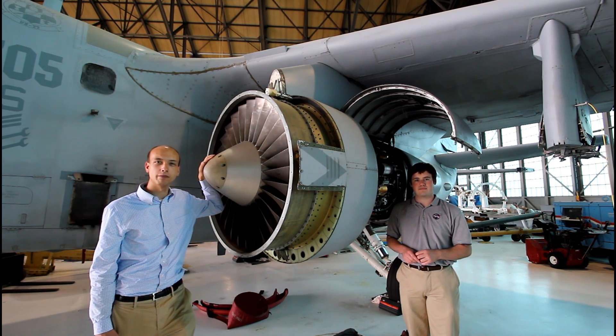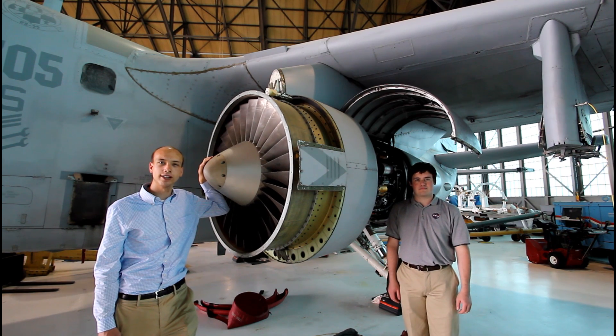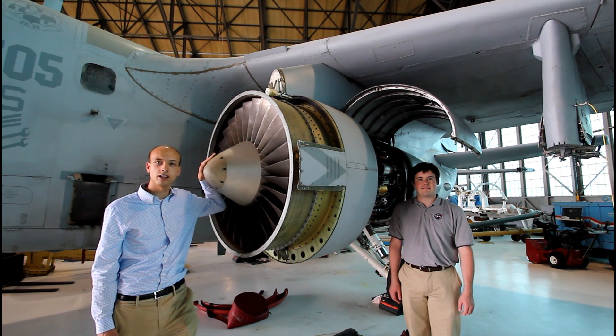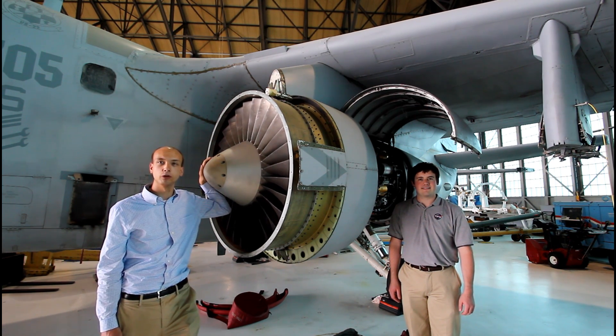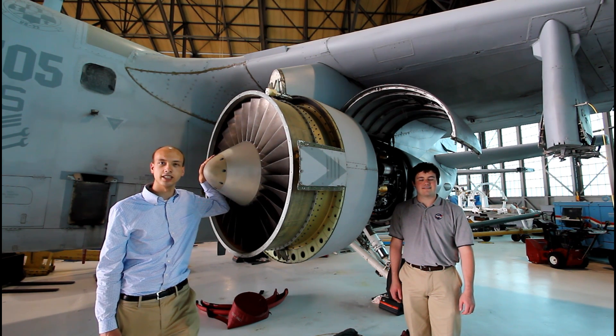The Advanced Powder Metallurgy Alloy, ME3, was developed in the NASA High-Speed Research Enabling Propulsion Materials Program. This alloy was designed to have extended durability at temperatures up to 700 degrees C in large disks. The higher-temperature capability of ME3 significantly improved the efficiency of jet turbine disks, and is considered a major advancement in disk alloys.